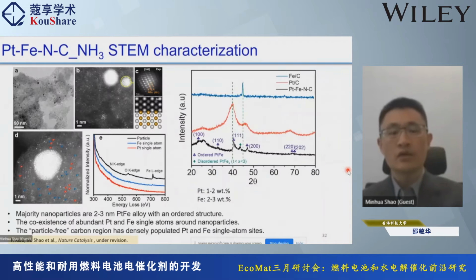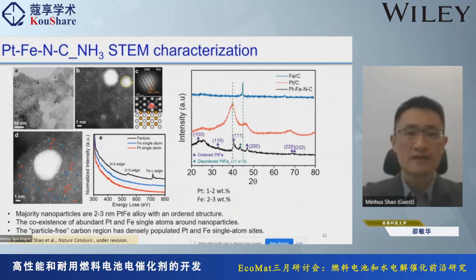Okay, so later we designed another method to synthesize this platinum iron nitrogen carbon. So we basically use ammonia treatment. Okay, so now we also see that there are a lot of single atoms, and then there are also nanoparticles, and the majority of these nanoparticles have the ordered structure. Okay, so it's also very small, 2 to 3 nanometer. And in these single atoms, using the EELS, we found that some of them are iron single atoms. You can see the blue line is a very weak iron, and the red is actually platinum single atom because we don't see this iron peak.